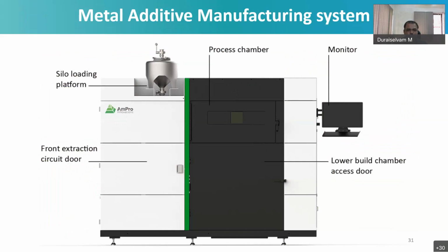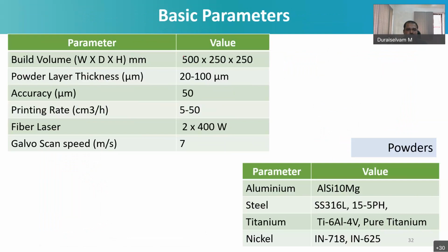And it has a huge build volume of 500 by 250 by 250. The powder layer thickness can vary between 20 micron to 100 micron, with a very good accuracy of 50 micron. And the printing rate is 5 cubic centimeters per hour to 50 cubic centimeters. And actually it's a twin laser system. Why we went for a twin laser system is that the productivity can be entirely doubled.